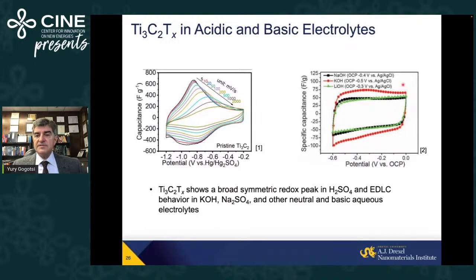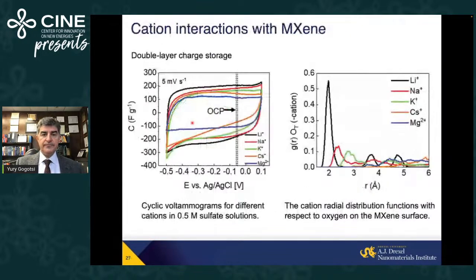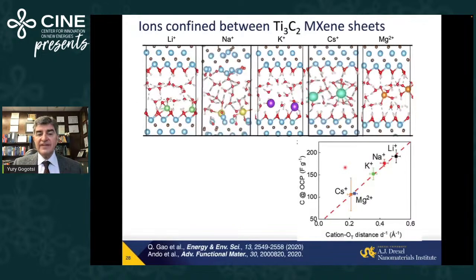You see cyclic voltammograms, a capacitive typical envelope. In acidic electrolyte, for example, if you take initially aqueous electrolytes, there is initially a double layer type of envelope, but at high negative potential, there is clearly a redox process happening here. And for double layer, depending on what ion we take in solution, you will see different shapes of cyclic voltammograms, different capacitance value,